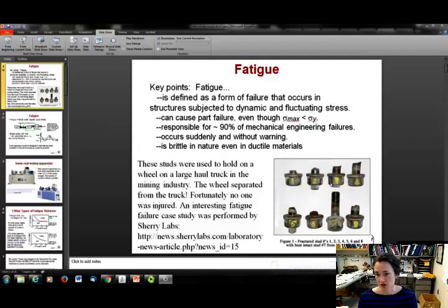So here in this picture, there was an interesting failure study done by Sherry Labs. The link is given below if you'd like to read the full study. But the gist of it is these studs or bolts were used to hold on the wheel to a big mining truck. And of course, the wheel just fell straight off one day after the parts had been in service for a long time. And they wanted to know what went on. It turns out that the bolts that they were using were okay for the service that they were being put to, but they were installed incorrectly, and that's why they failed. But they failed after a certain amount of use and just all of a sudden without warning. So they were interested in doing the failure study.